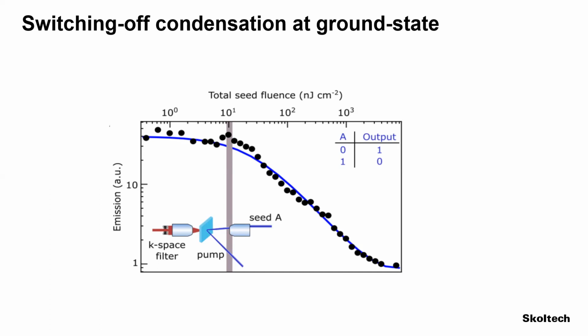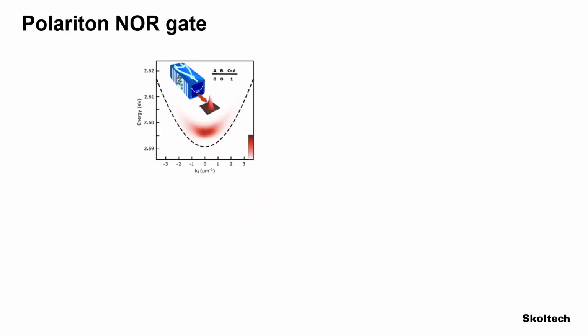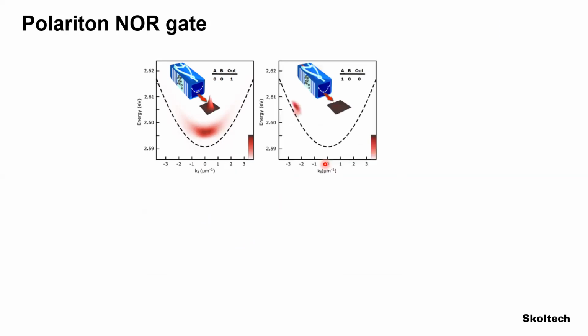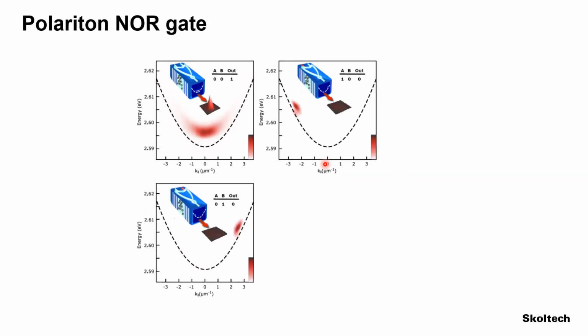Now let's use the fact that we have a polariton dispersion. So let's compile now the NOR gate, the first universal gate. Without any input, and my inputs will be coming at two in-plane, opposite in-plane wave vectors, I get the emission from the polariton condensate. If I put the seed beam here, I switch off the emission from the k equal to 0 state. If I put the control beam there, again I switch off. If I have both of them there, both of them get amplified, and I still switch off the condensate. If I compile these four elements, it is the NOR gate.